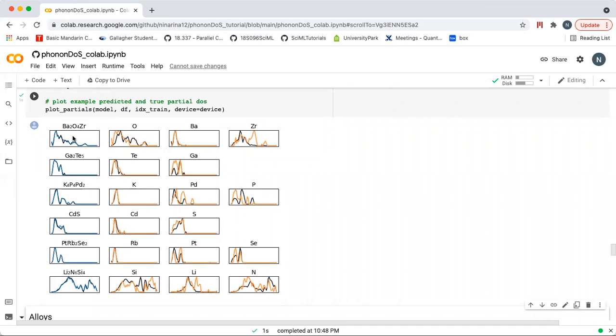So in this plot, the leftmost column again shows our total phonon density of states for both the prediction and the ground truth. And the remaining columns show the partial phonon density of states in black, overlaid with the learned node feature for that element in the colored curve. And since the network wasn't explicitly trained to predict the partial phonon density of states, it's very interesting to see that there's actually some correspondence between those 2 quantities for many of the elements shown here.